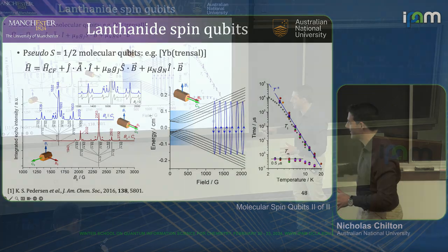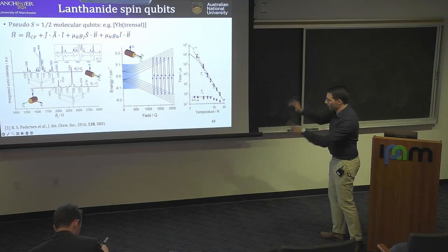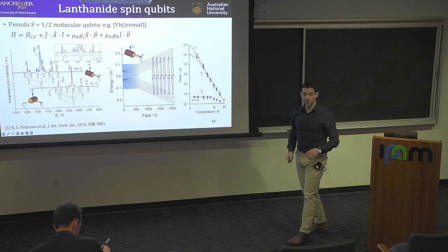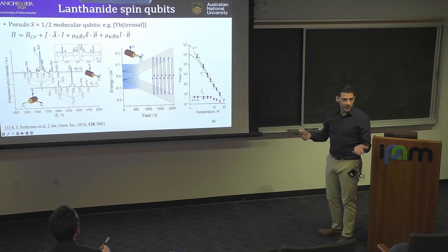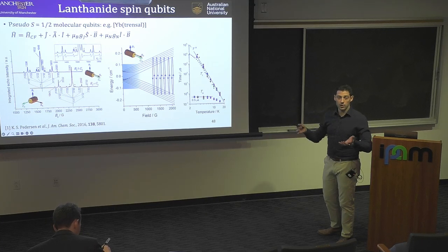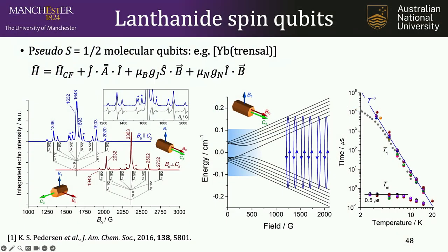Any questions on the ytterbium? Right — so complicated electronic structure, complicated molecular structure, complicated EPR spectra, but it's cool. You can do phase memory experiments, echo experiments on these things, and you can pick whichever hyperfine line you like. This is looking at a T2 phase coherence time on the order of some microseconds, which is perfectly fine if you're doing nanosecond pulses. This has to be at quite low temperature to see what you want.